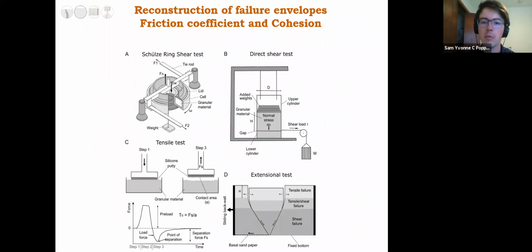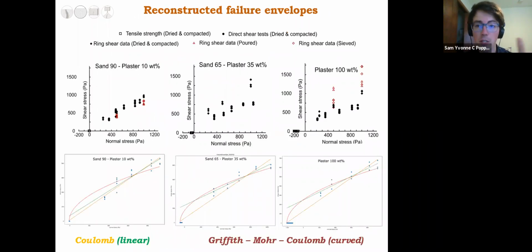So really a pretty complex behavior. And we then ran, because those ring shear tests are pretty poor at constraining the cohesion of granular materials accurately enough, a series of direct shear tests and tensile tests to constrain the failure envelope of each of our materials. I showed 3 examples here.